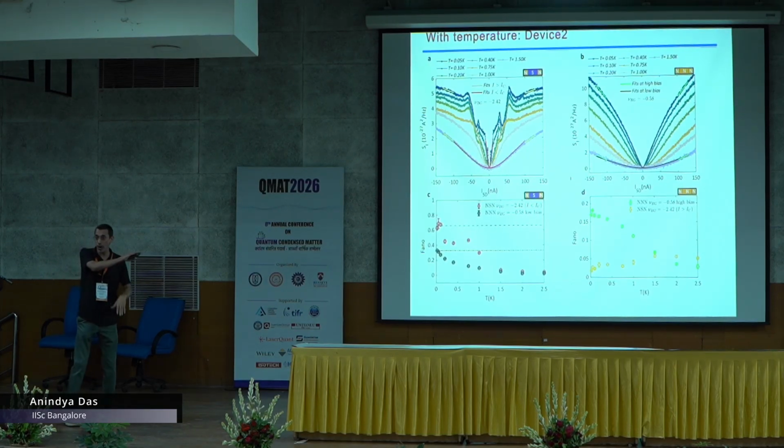And we have done not only a single point, but also as a function of filling variations and so on. And this is the temperature dependence. Again, in the superconductivity phase, if you increase the temperature, this Fano doubling decreases, and above Tc they go to the higher Fano values. Most importantly, this suppressed Fano that we see is weakly dependent on the temperature. On the other hand, the Fermi liquid Fano is highly dependent on the temperature. For that, a monotonic decrement is expected in the theory using electron-phonon coupling, but for the suppressed Fano, the temperature behavior is again anomalous.